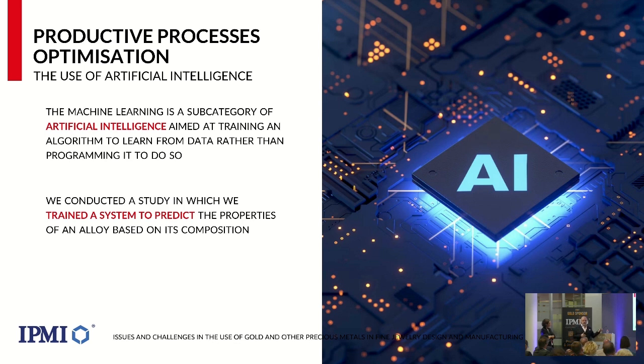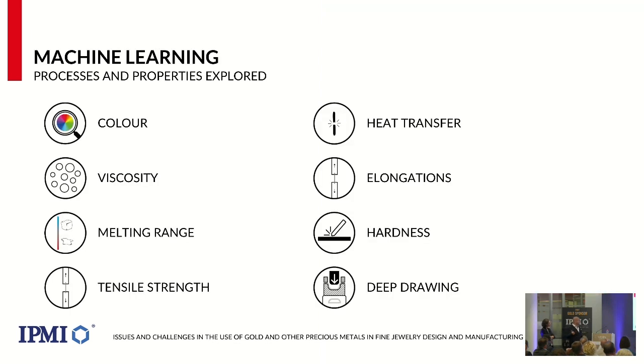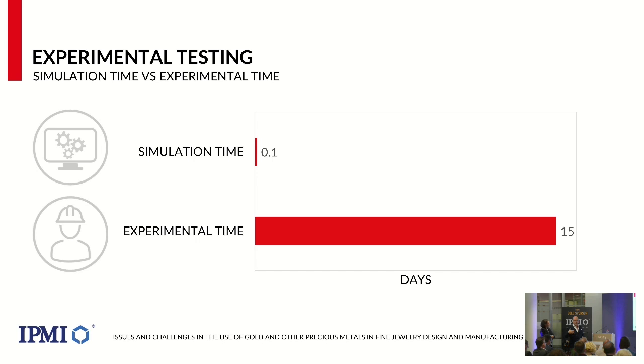So starting from another recipe, what would be the characteristics? The characteristics that we were checking were the color, the viscosity of the molten metal, the melting range, the tensile strength, the heat transfer, the elongation, hardness, and deep drawing. Usually it takes something like 15 days for an R&D person to do the characterization, because we have to prepare the sample and measure every single characteristic, and it has a lead time of 15 days compared to a simulation time of a couple of hours.